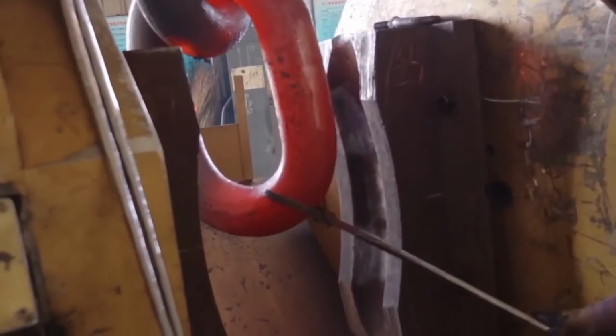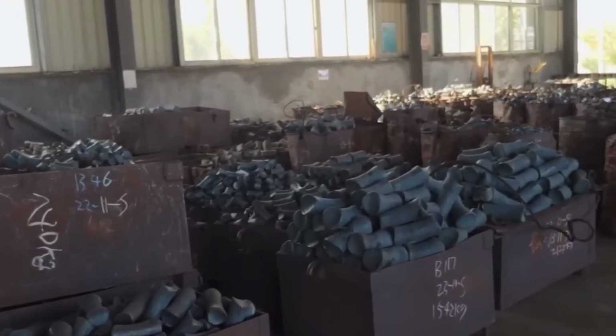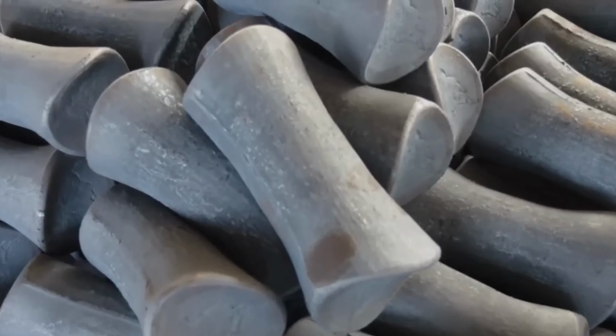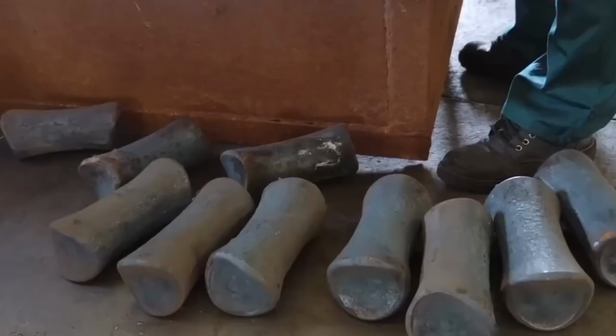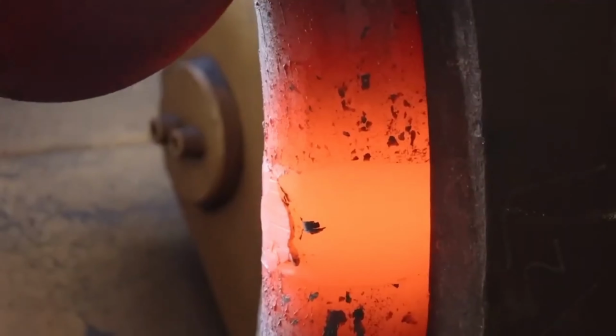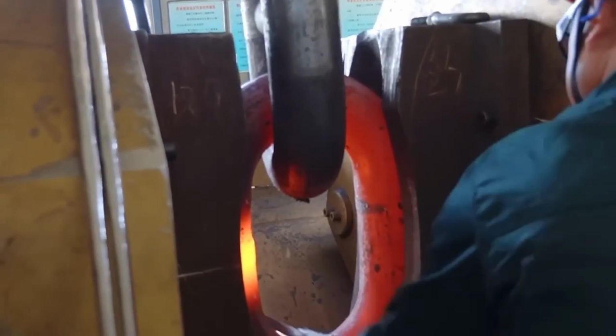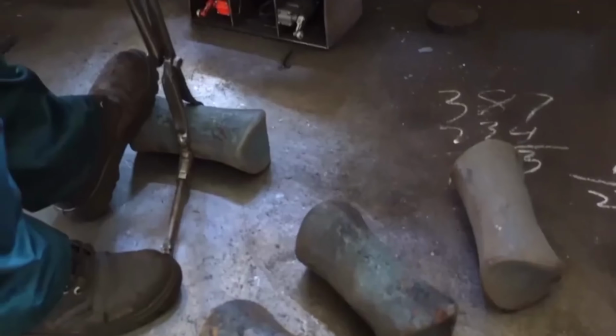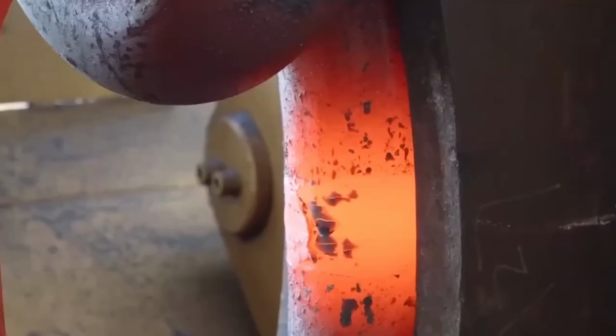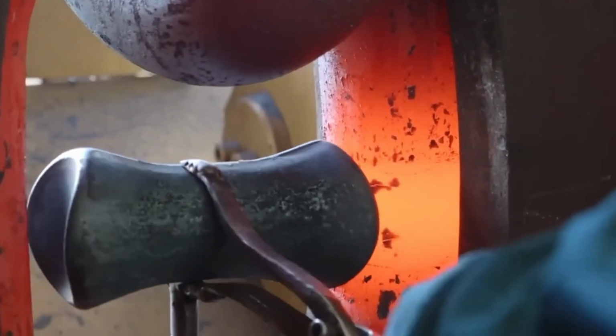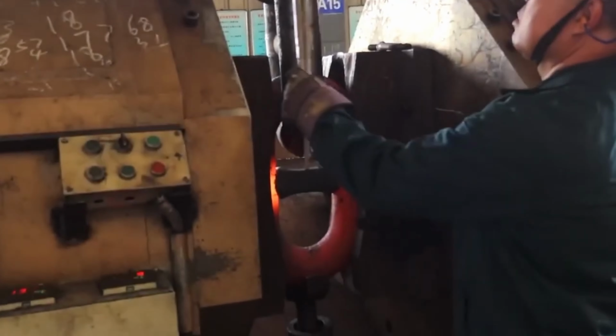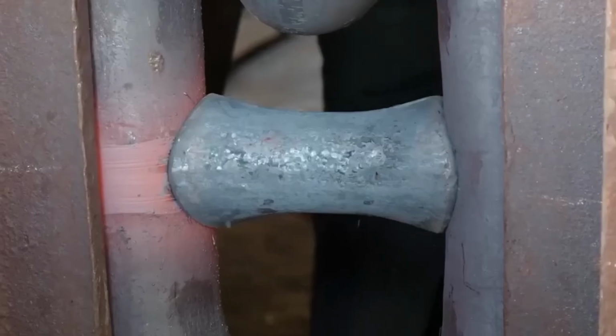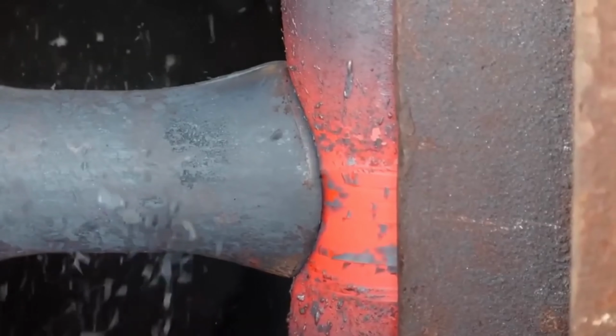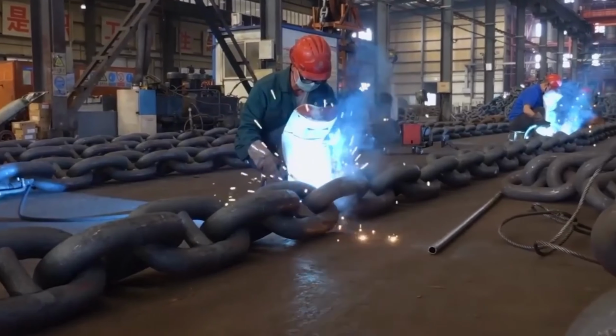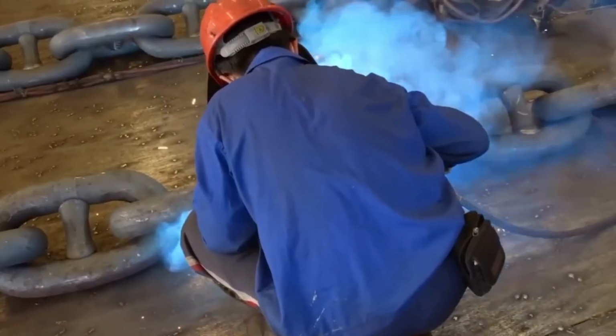The goal is to create steel capable of resisting both sudden impacts and constant heavy loads. Each batch's temperature profiles are monitored continuously by automated sensors. Even a 10-degree deviation can weaken the chain or create internal stresses. Once heat treatment is complete, the chain passes through specialized shot blasting machines. These machines fire thousands of tiny steel beads at high velocity against the chain surface. Shot blasting removes scale, smooths rough spots, and improves fatigue resistance by introducing beneficial compressive stress on the surface of each link. After blasting, the chain looks clean and uniform, but the process is far from over.